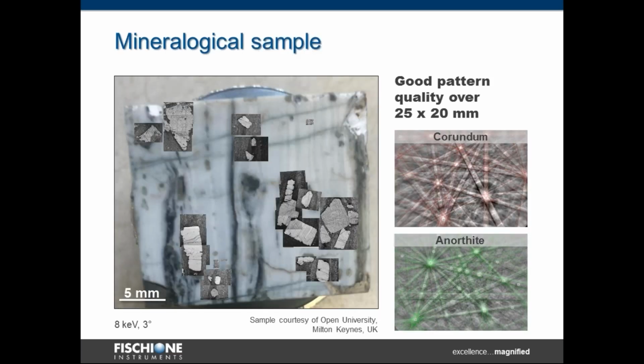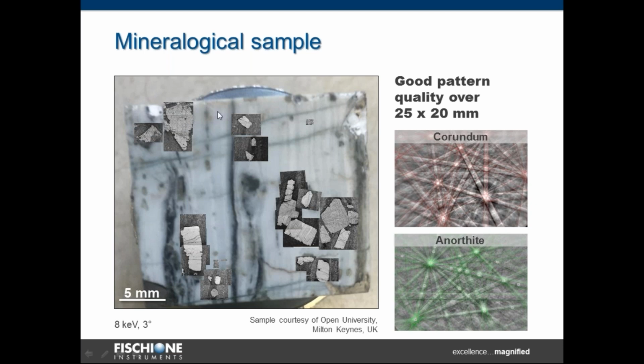Another very interesting example is a multi-phase mineralogical sample, which has some porosity, which makes it very difficult to prepare with any sample preparation technique. This sample has dimensions of 25 by 20 millimeters, and it is made basically from corundum grains, the big grains here, surrounded mostly by anorthite. As you can see, we obtained a good quality EBSD pattern across the whole surface of the sample, which is quite big.